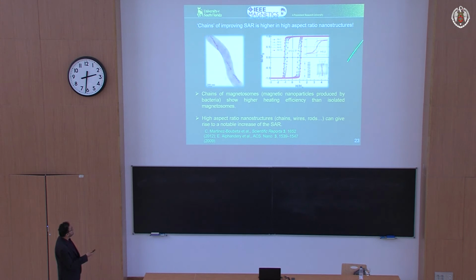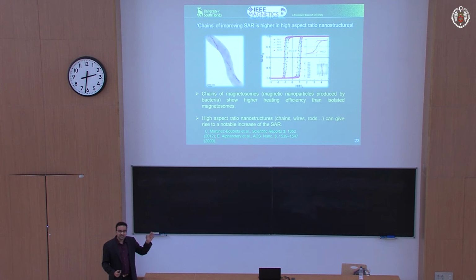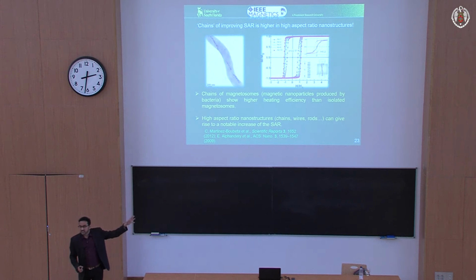So here's the result from the Basque Country, reported in these papers many years back. They actually looked at the SAR of the bacteria with the chains, and they found very impressive SARs. So the clues are pointing towards high aspect ratio anisotropic nanoparticles as being the most effective for optimizing the heating efficiency for hyperthermia.